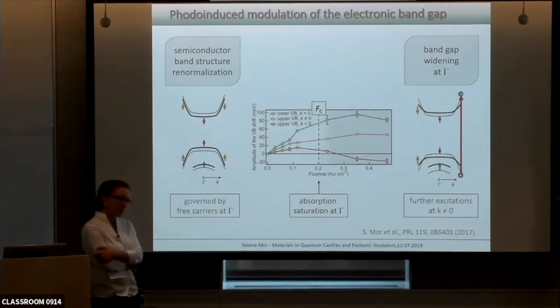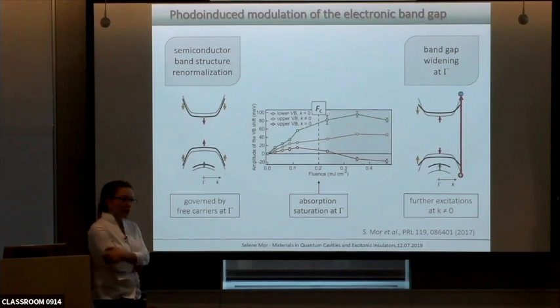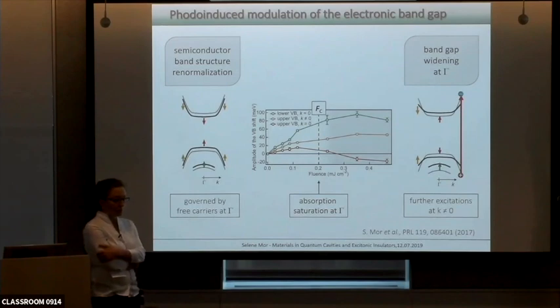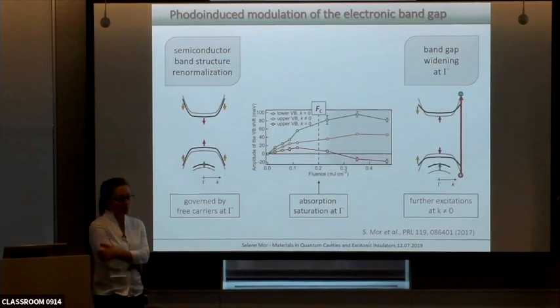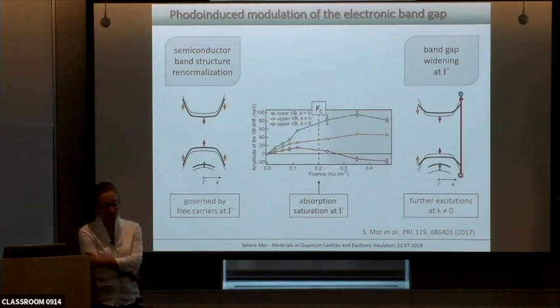But I think the message you're saying, however, is that you don't see anything happening at all in the middle of the gap. Everything is at the band edges, right? Mm-hmm. But I should be starting to produce localized breaking of symmetries that would allow the system to create mid-gap states in some transient way. That's what you see in the polyacetylene type stuff and all of the things we were used to in 1D, in charge density wave systems.